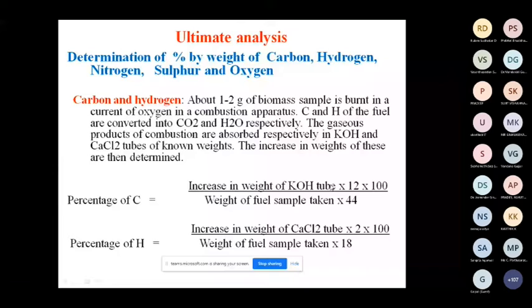Similarly, hydrogen: water molecular weight is 18, 2 is hydrogen. For 18, you have 2. So the increase in the calcium chloride tube will give you the total hydrogen content. For the weight of the sample, you can calculate the percentage weight of hydrogen content in the fuel. This is the way for carbon and hydrogen.